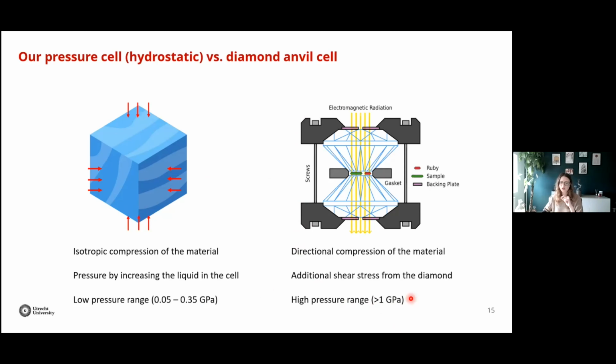So now you might wonder, okay, but what's the problem? Of course, if we want to have our device that works, I mean, we cannot have a device that works under pressure. So we have to implement this pressure or strain through fabrication. And that's something that we can do for low pressure range. So we can have this type of pressure during fabrication, but we cannot have gigapascal pressure during fabrication. So for example, playing with substrate and thermal expansion coefficient can result in this type of strain, but not in this type of strain. So this is too high.